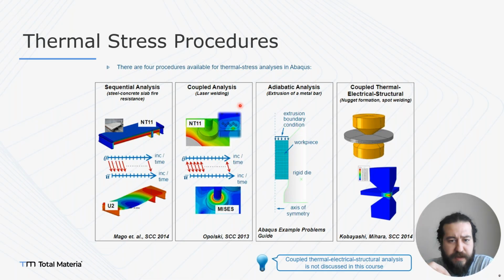On the other hand, if you're looking at an adiabatic analysis, for example a forming analysis, you might assume there is no heat effect, but there actually is one: the inelastic heat fraction. Mostly 90% of the total plastic dissipation energy can be converted to heat. So even in cold forming, you may need to be concerned about plasticity, because of the inelastic heat effect. It directly changes your springback and the plasticity curve. You need to consider it if you have really big strains.